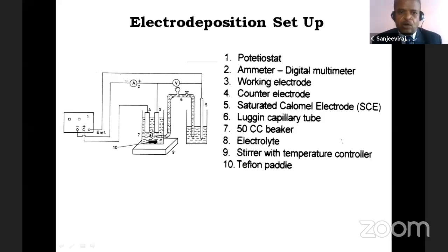From the solution, the constituent elements will be released because of your external potential, and the ions will be deposited on your substrate. For example, if you want cadmium sulfide, it will be deposited on your working electrode. Here, the solution is cadmium chloride and thiourea, or for example sodium sulfide. These two analytical grade chemicals should be taken in a particular proportion and molarity so as to have the stoichiometry in your material. That is called electrodeposition. Here you have to keep the potential constant with respect to a reference electrode such as SCE or a hydrogen electrode. And that is the technique called electrodeposition.